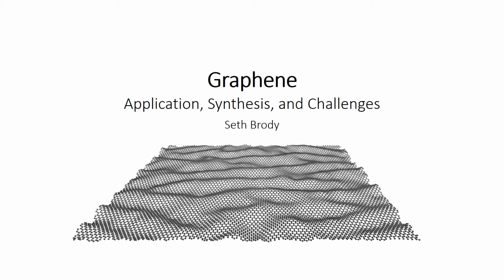Copper thickness independence was seen for surface catalysis through self-limiting substrate solubility and saturation, and reasonable quality via room temperature extracted carrier mobility and residual Dirac density, but less effective than mechanically exfoliated equivalents.